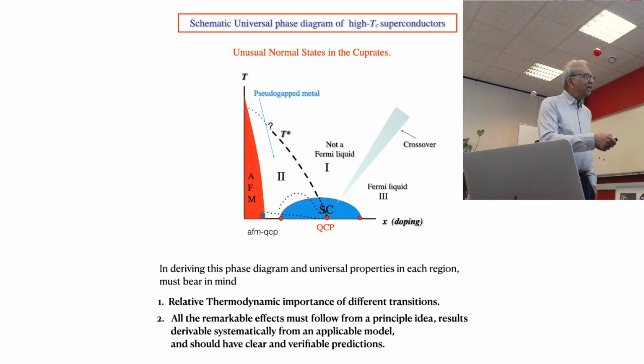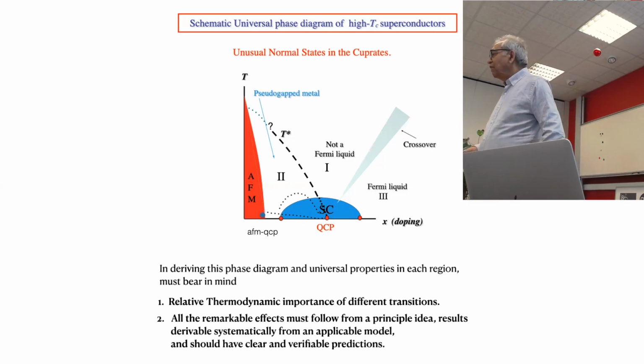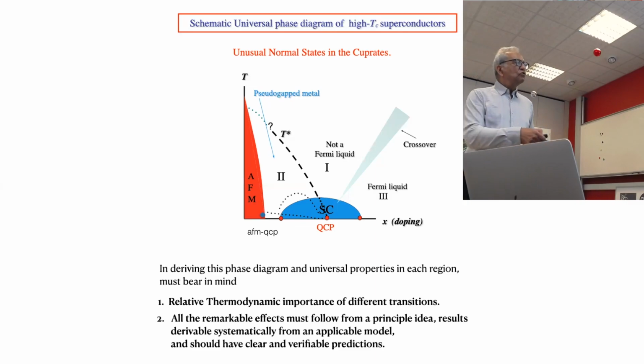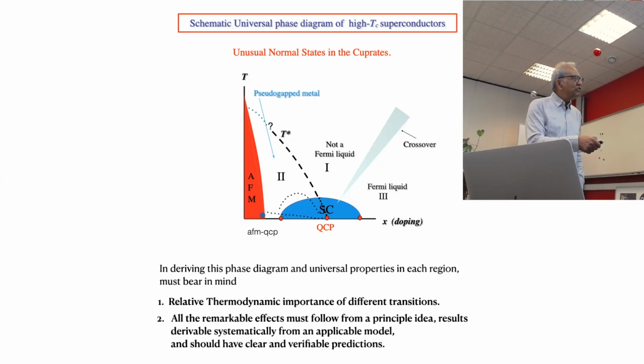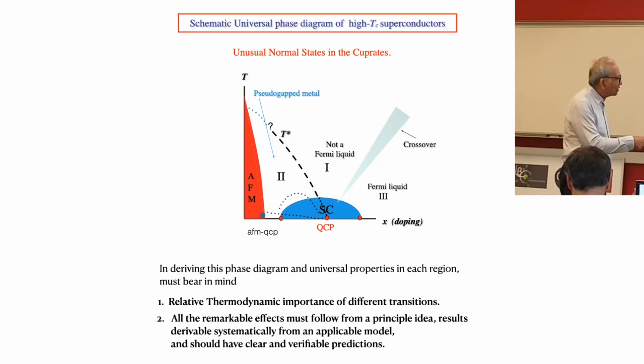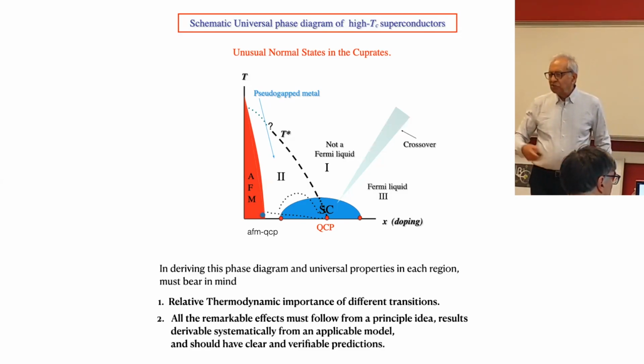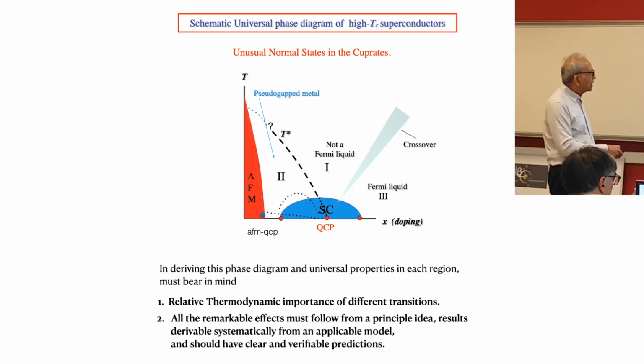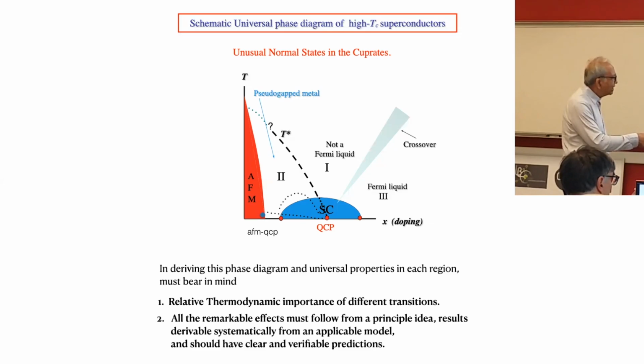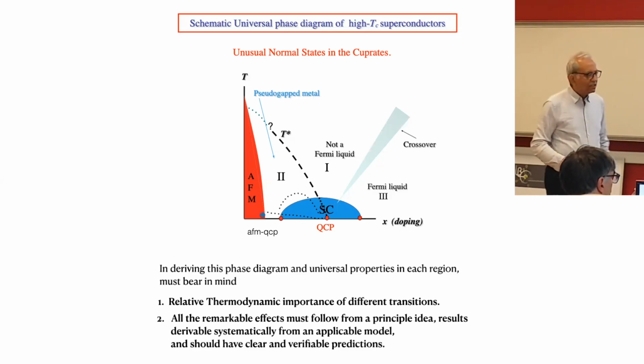And from the entropy change here, we know that somewhere around here, the change of energy going from there down to, let's say, the superconducting transition temperature is twice or thrice the change in energy from the superconducting transition. So this is a major effect, and you can measure it here, and it becomes superconducting, and you have to destroy superconductivity with magnetic field or something to continue this. Similarly, in here, there are remarkable properties. To continue down to low temperature requires some technique to reduce superconductivity. And then there is what I will describe as a crossover.